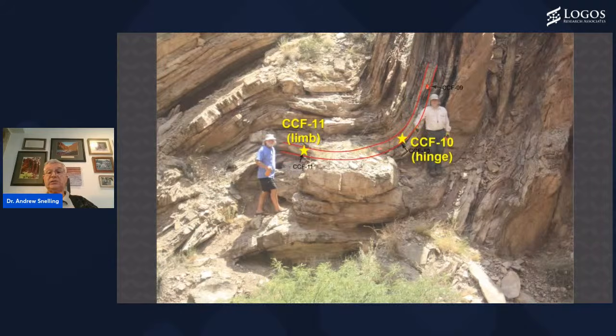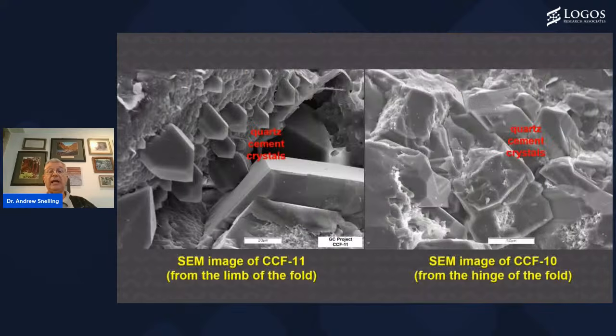And so here's samples now 10 and 11 in the Carbon Canyon Fold. Let's look at them under the scan electron microscope. Look at these beautiful terminated crystals in the limb zone sample. And yet we can see similar ones, not as pronounced, but you can still see terminations and flat crystal surfaces in the cement in the hinge zone of the fold.